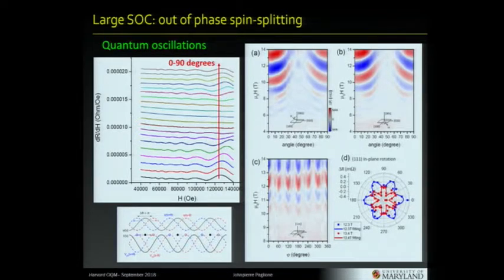You can see that at some point the oscillations completely disappear. And we were baffled by this for some time. If you compile this data in a nice color plot, you can see this is the oscillation here versus field, and then you change the angle and you see that this thing just disappears at 45 degrees. You can do something fancier, which is, sorry, you can't see that, but if you point the field along 111 and then rotate about that, you can see a six-fold oscillation disappearance, which is consistent with the special angle being 110. We've worked this all out.